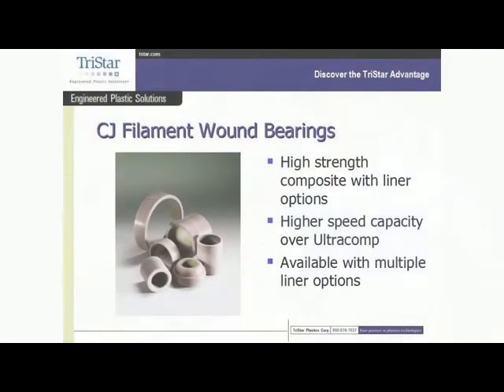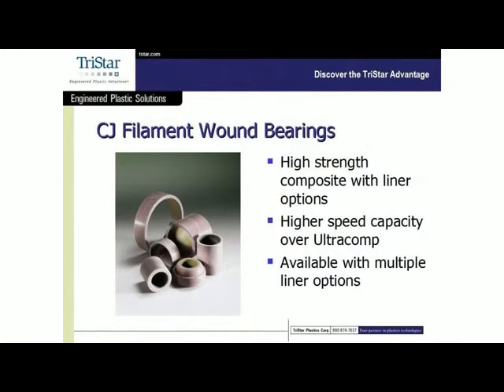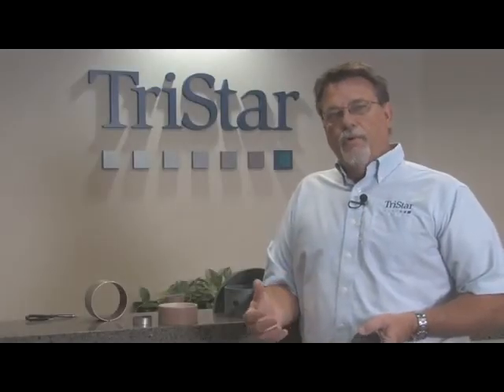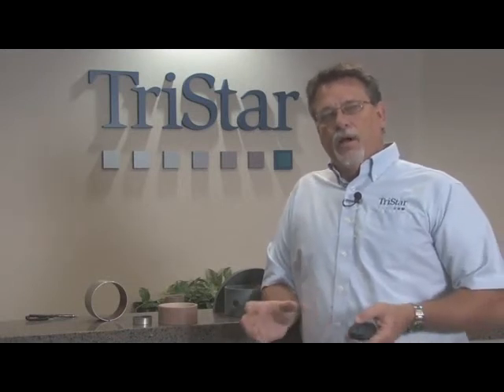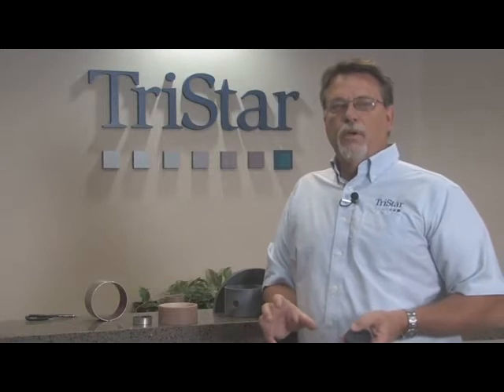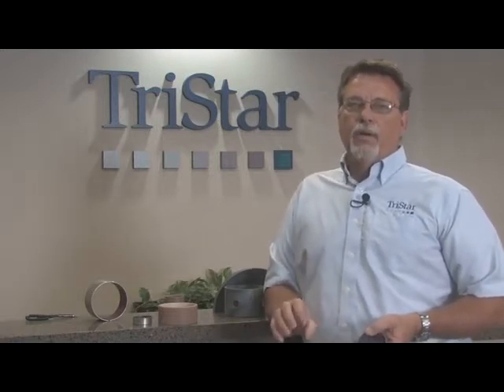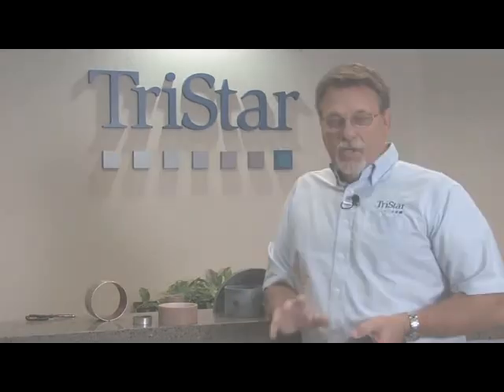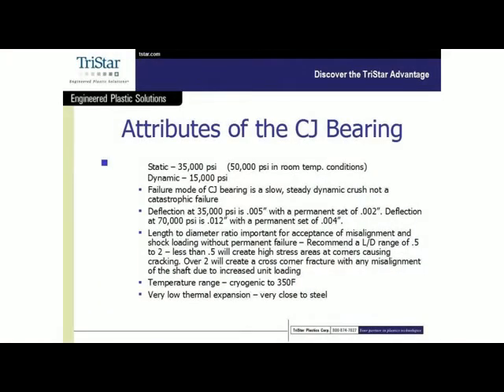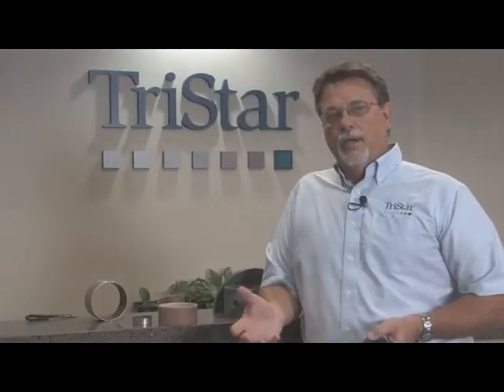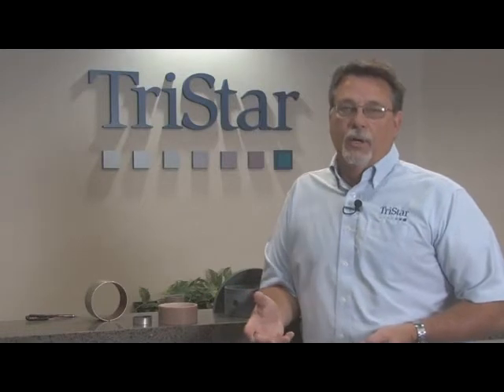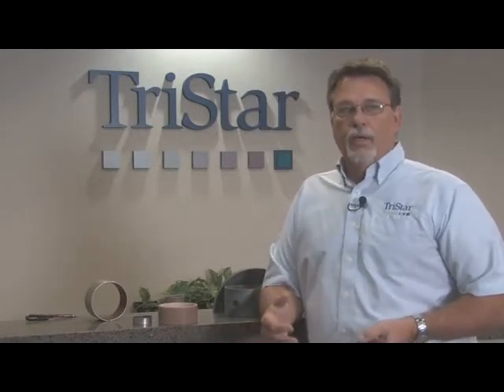This material has a higher speed capacity than the UltraComp does. UltraComp is fairly low because it is a highly insulative material. So we tend to use the UltraComp more for applications where it's low speed oscillating, some possible low speed rotary applications, but we prefer to keep it into low speed oscillating. With the CJ, just by the nature of its makeup, we can go to higher speeds. With the actual CJ grade, up to 100 feet per minute unlubricated, and with the lined grades like the FCJ or the Super CJ, we can go upwards of 500 feet per minute, again without lubrication.